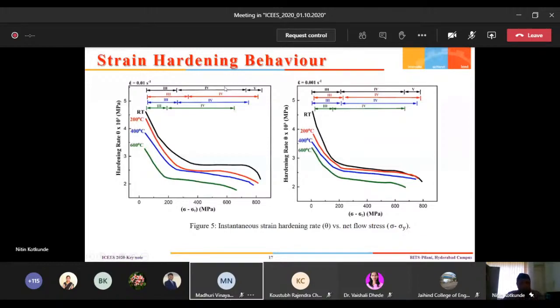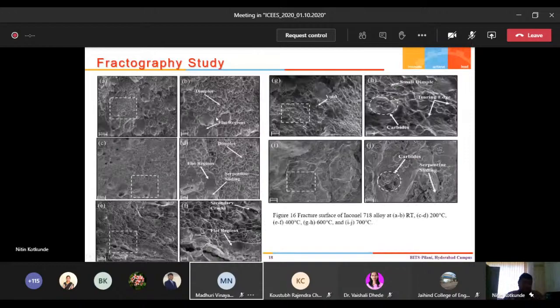Then we have done the fractography study. We took the broken tensile test specimen, in the thickness direction, as a sample for the fractography, and we realized that there is a mixed granular fracture having some flat regions as well as dimples. Dimples indicate a ductile failure, and flat regions indicate a brittle failure, which also confirms a DSA region here. And some voids are there, and some carbide particles are there. Their compositions we have tested using XRD and EDX. That detail I am not presenting here.